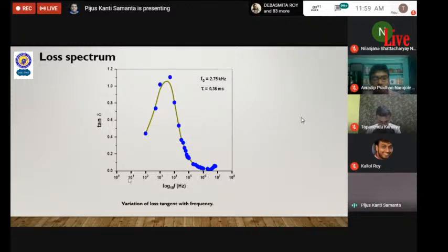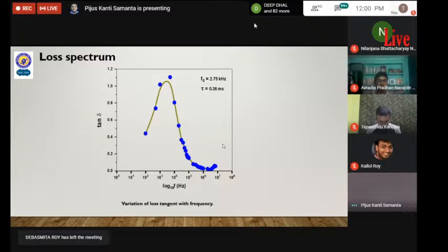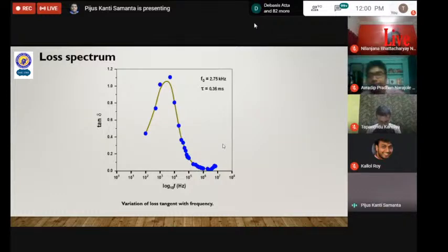which shows an initial increase of the loss tangent to critical values up to 2.75 kilohertz, and it gradually decreases for higher frequencies. This is because, as we know from the theory of dielectric polarization, on application of an alternating electric field in a dielectric sample, the dipole tends to oscillate with the frequency of the applied field. But beyond a certain frequency, the dipoles may no longer be able to follow the oscillations of the electric field, and the oscillations of the dipoles become out of phase, leading to the dissipation of energy.